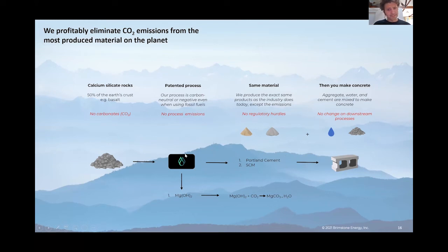But what that means is from a single plant, you can make both Portland cement and SCM, and therefore make the exact same cement that's used today, no difference whatsoever. And then you can make the exact same concrete and building material that's used today, no difference whatsoever. So if a cement company were to use our process instead of the dry process, which they use today, then they could vertically integrate their production of SCM, which could be of huge financial benefit to them. So in this way, our process could be lower cost, and it can also be the same material, and it can also have zero process emissions.